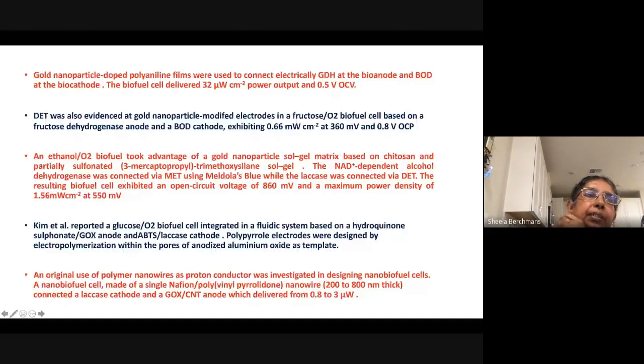Also, there are many other examples, like gold nanoparticles along with polyaniline being used with glucose dehydrogenase at the bioanode and bilirubin oxidase at the biocathode. The biofuel cell delivered 32 microwatts per centimeter square power output and 0.5 volt OCV. Another example I can tell you here is a gold nanoparticle sol gel matrix, which delivered a power output of 1.56 milliwatt per centimeter square at 550 millivolts.